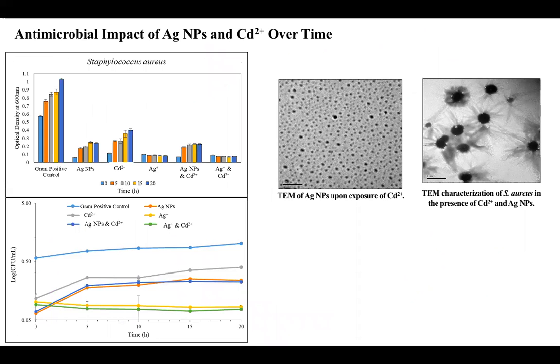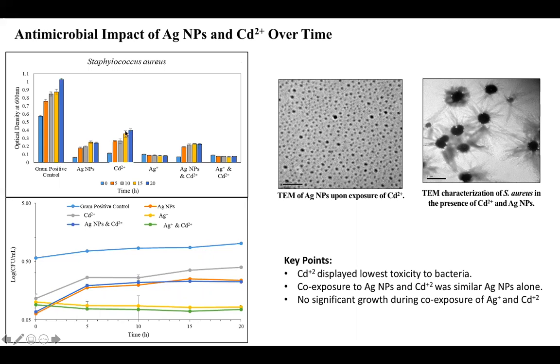All right, so from that, we were able to compare the antimicrobial impact of silver nanoparticles in each heavy metal. By first looking at Staph aureus and cadmium, we can see over that 20-hour time frame that there's a difference in our bacterial strain growth. Cadmium had the least amount of toxicity to Staph aureus on its own, and silver ions the most toxic. So as our control groups independently, they all had different responses.